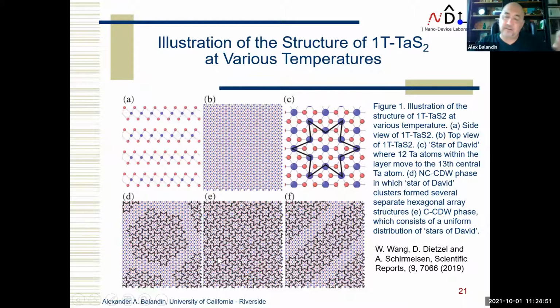And in this material, there is no abrupt transition from metallic state to commensurate charge density wave. It undergoes several intermediate steps. One intermediate step is nearly commensurate, when you have domains which are commensurate with this new crystal structure periodicity, surrounded by an incommensurate phase, which you can think about as a sort of domain walls. And you also have an incommensurate phase, when you're losing translation symmetry, which is closer to metallic.